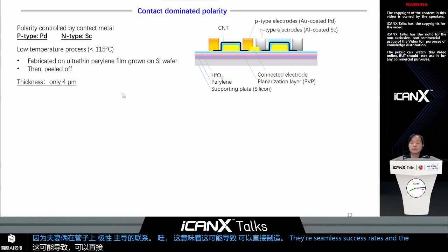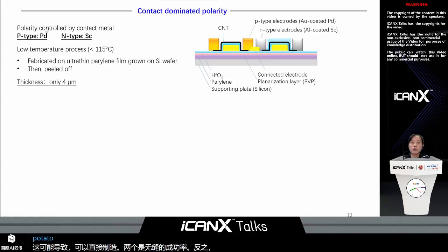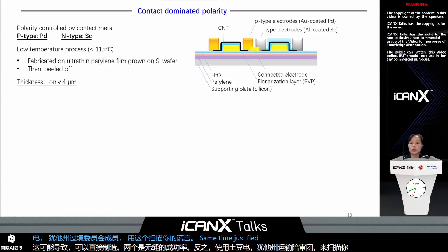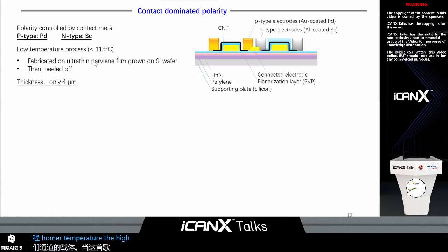In this system, we use palladium as the electrode for the P-type transistors, and we use scandium to realize the N-type transistors by injection of different kinds of carriers into the channel. During this fabrication process, the highest temperature can be well controlled below 115 degrees, and the thickness of the whole system can be controlled around several micrometers.